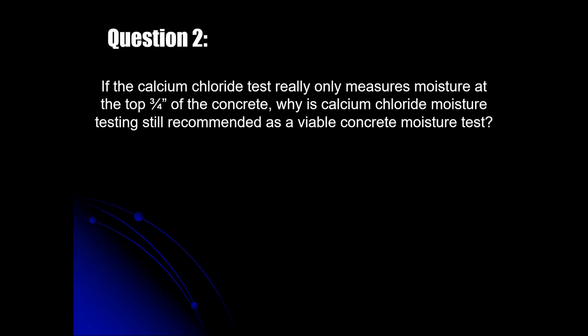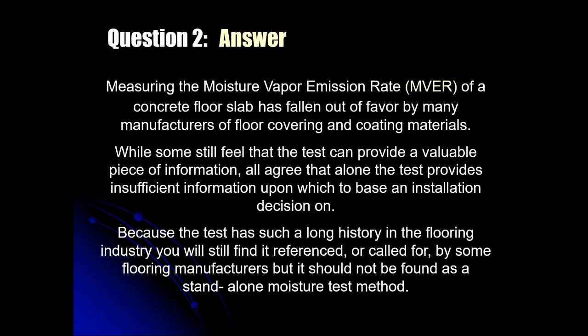So question two was, if the test only measures moisture in the top 3/4 of an inch, why is it still recommended as a viable concrete test? Well, it has absolutely fallen out of favor in a lot of circles, but because it's been so widely referenced and used over many decades, there's a reluctance on the part of some people to completely get rid of it, even though 2/3 of the people on our ASTM committee that writes the standard for it are ready to get rid of it already.